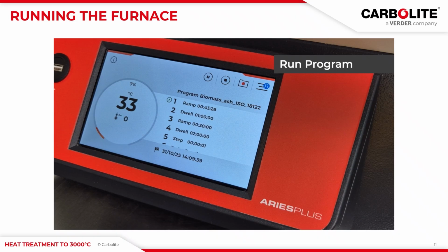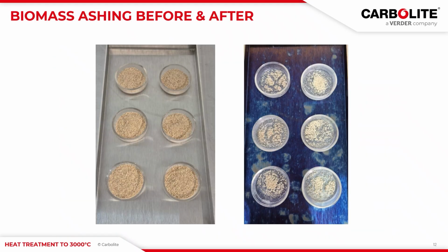Here we see key stages of the biomass ashing process for ISO 18122. On the left, you can see biomass sample materials placed in crucibles, prepared for analysis, ground to a specific size and dried. And on the right, the same crucibles are shown after the heat cycle, containing only the resulting ash.